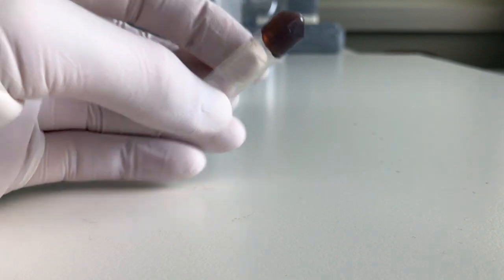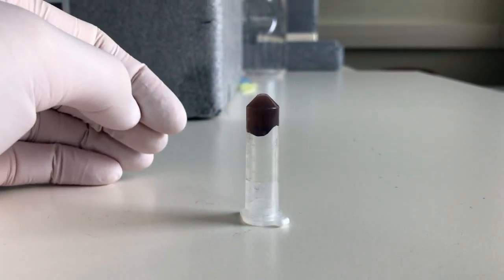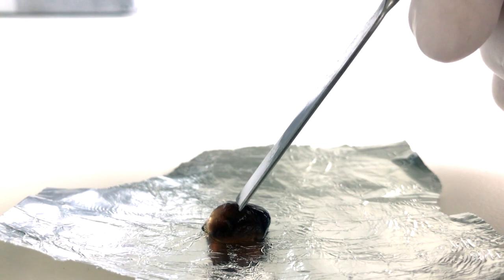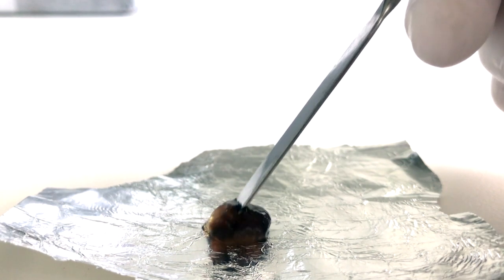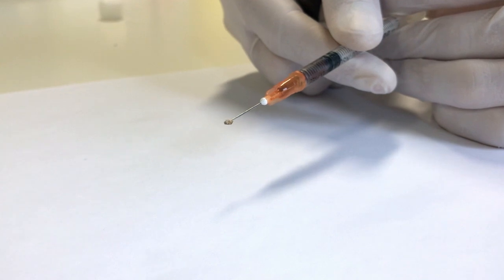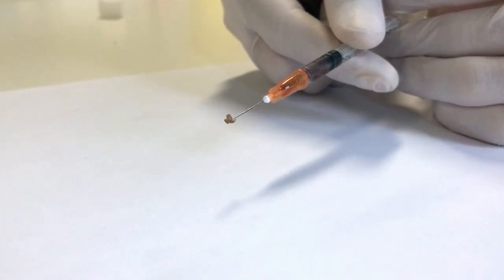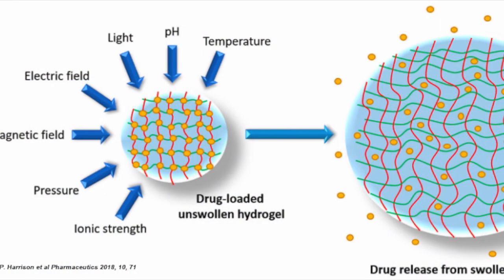Prepared hydrogels are three-dimensional polymer scaffolds with the ability to swell in aqueous media. Hydrogels can overcome the low solubility of many photosensitizers in polar media while also preventing the premature release of the drug. Injectable properties of the formulation allow for local delivery of the hydrogels, where thanks to the self-healing ability they will reform at the injection site and allow for controllable pH-dependent release of the drug molecule in a slightly acidic tumor microenvironment.